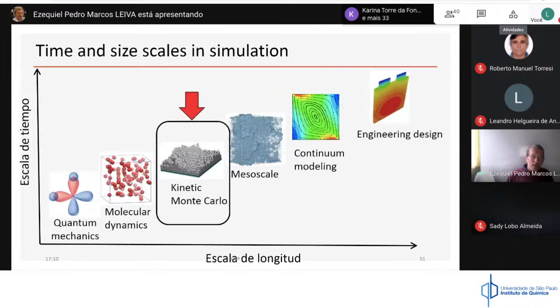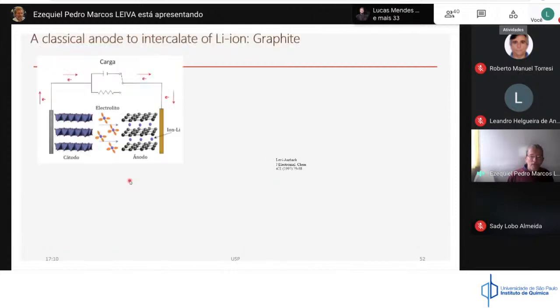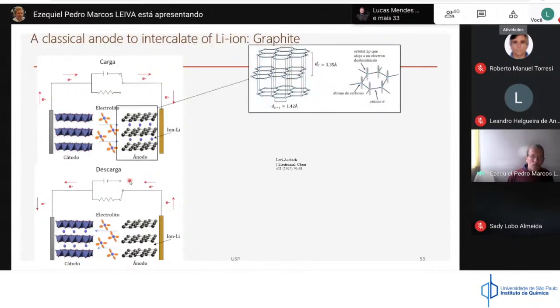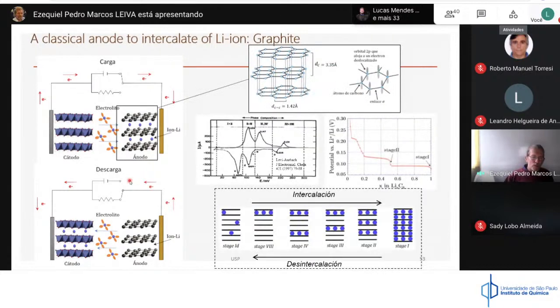The next technique that we'll address is kinetic Monte Carlo simulations. Kinetic Monte Carlo simulations is another tool. Graphite is a system we'll go deeper into in the battery, but it's the same as before. You have an anode which is made of graphite, and lithium is inserted in this graphite layer. And when you look at the voltammetric behavior, you will find that lithium has a number of processes where lithium is inserted in this material.